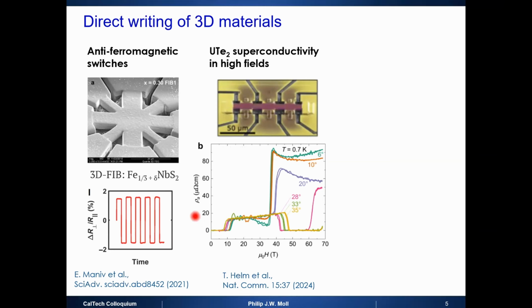It really is not. Here you see resistivity as a function of field. It survives up to 10 Tesla, which is already far above its Pauli limit. But then superconductivity comes back in the 50 Tesla range and really survives up to 70, 75 Tesla. So you have something that superconducts at 70 Tesla, but has a TC of 2 Kelvin.